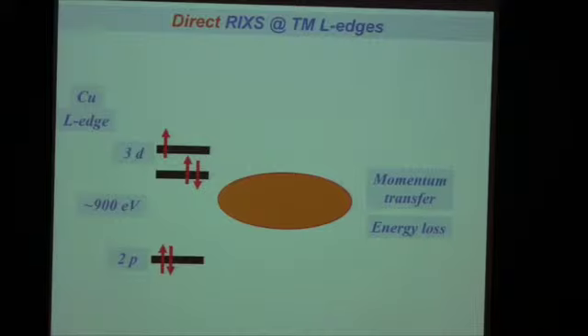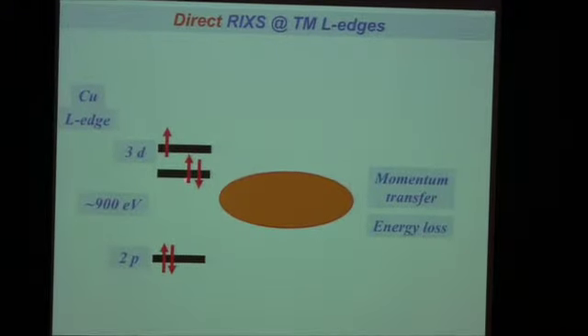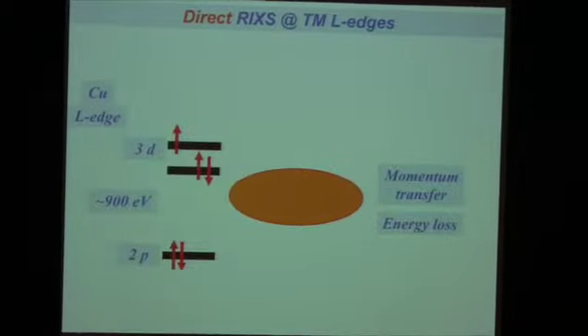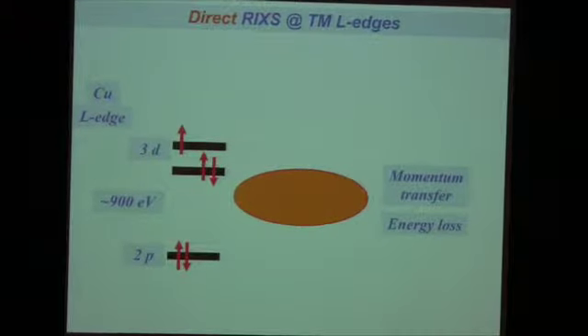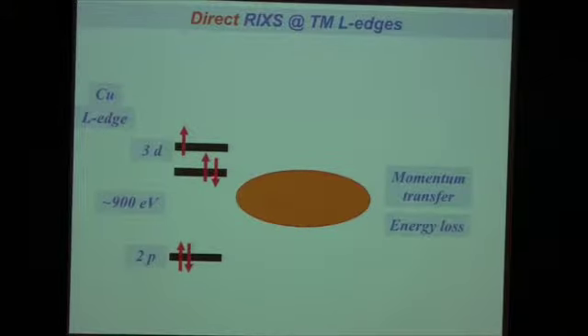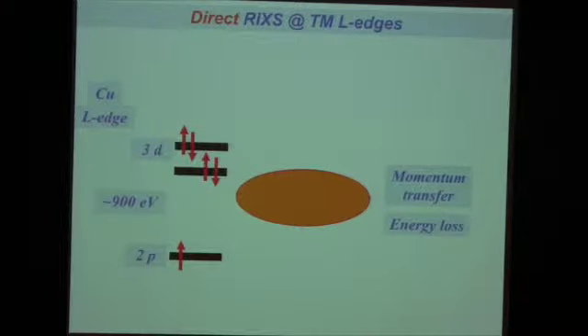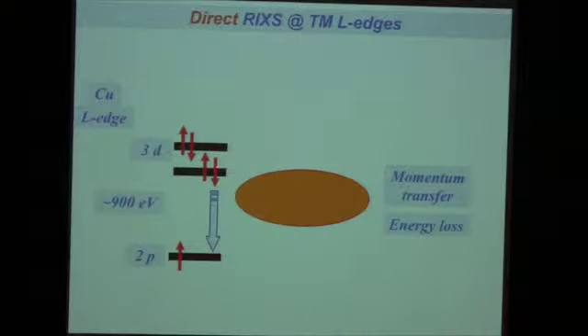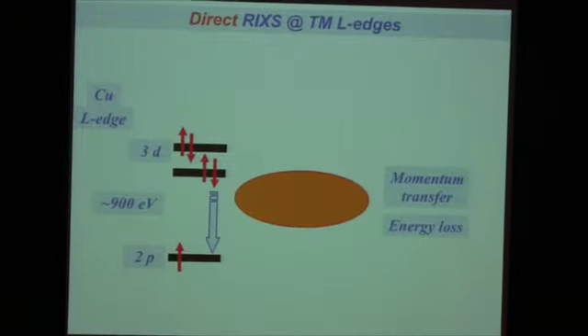Well, there is. So now let's look at the same picture as I did before, but now introducing the spins. So now here's the hole in the x squared minus y squared orbital. This is now a filled other T2G orbital or EG orbital. And here's the core. I come in with a photon, promote a down electron out of the 2p core into the 3d shell. Now what can happen is that, as I've shown before, the down electron out of another orbital can fill this core hole, emit a photon, and leave a dd excitation. That's okay.